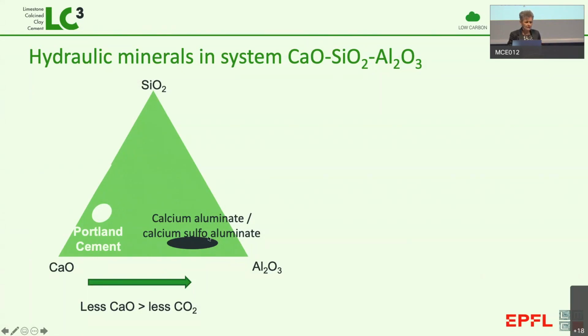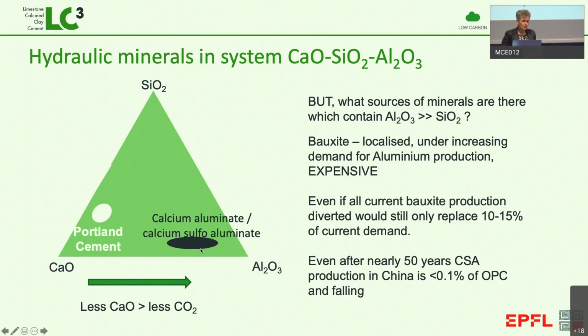And at first sight, this is very interesting because this black area here is further away from this corner here. That means it contains less calcium oxide and therefore less CO2. Unfortunately, life is not so simple because the problem is to form these compounds, we need to have minerals that contain much more alumina compared to silica. And this brings us to minerals like bauxite, which is much more locally distributed. It's expensive. Of course, it's used to produce aluminium.